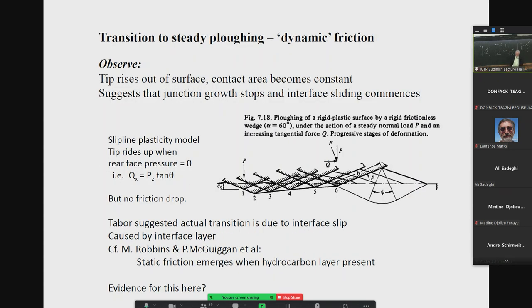So this is a kind of semi-summary of where we are. What we've seen is you make a hole, you apply some lateral stress, and the thing goes into the surface a little bit further. This is actually from Ken Johnson's book, his work in the 90s, on ideal plasticity, the slipline field theory. I don't think anybody does that anymore. Essentially what you can see happens is that you generate on one side a wedge of material. In fact, there's a whole engineering industry in this because if you get the angles right, this thing doesn't turn into a blob. It turns into a chip, which comes away, which is what's happening in metal cutting.